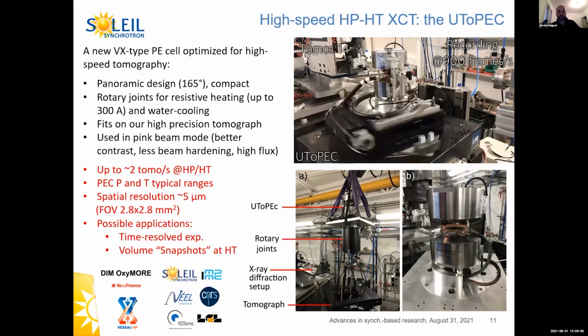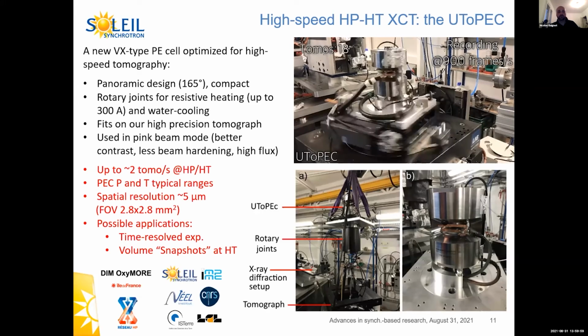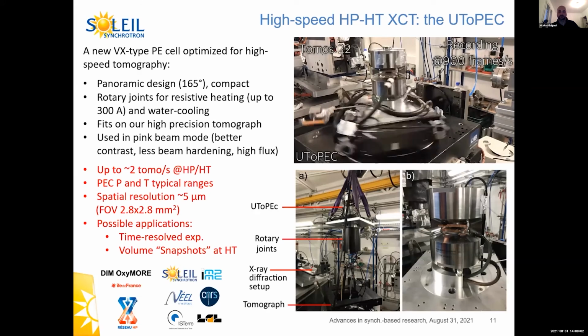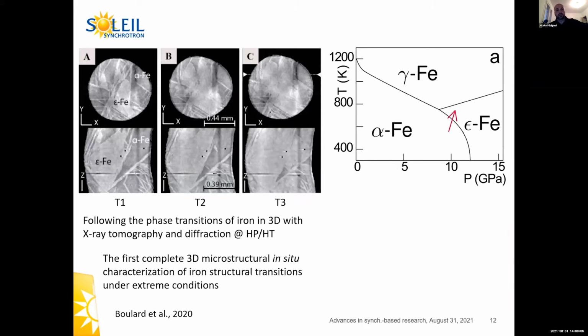Possible applications are time-resolved experiments and snapshots of sample volumes at high temperature. One of the first applications of this technique was this paper by Boulard and collaborators published last year, following the phase transitions of iron in 3D with X-ray tomography and diffraction at high pressure and high temperature. I'm just showing the transition from alpha to epsilon iron. On the left, you see the starting sample was a single crystal of iron. And you see here the epsilon iron platelets growing with time during the transition.